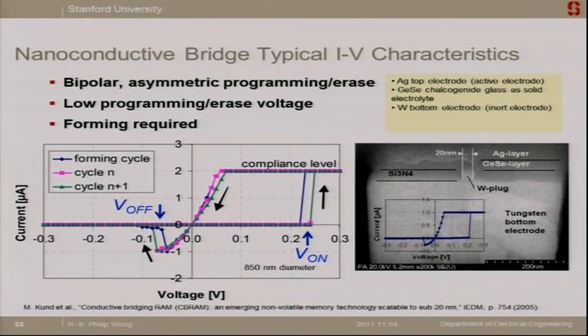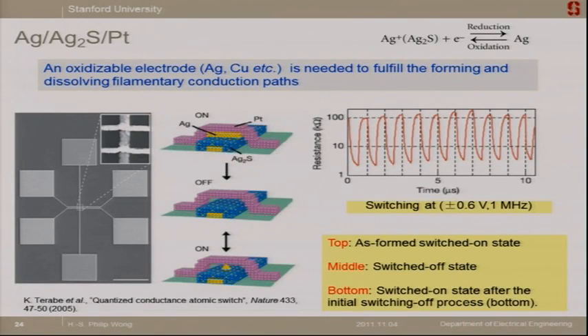So here are some IV characteristics. You start from the high resistance state. Then it starts touching, and you can go in the other direction to make it untouched again, disconnected again. You can actually scale it down to an atomic scale. This is a very interesting paper from Terabe-san showing a platinum and silver sulfide and silver electrode, and you can basically do tiny, nanoscale electrode plating and have one atom touching and not touching, which is sort of the ultimate scale of these kinds of devices.